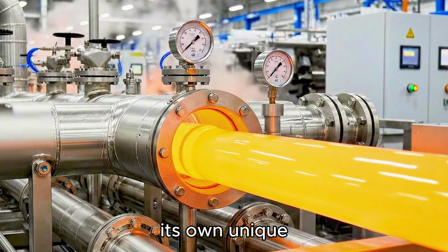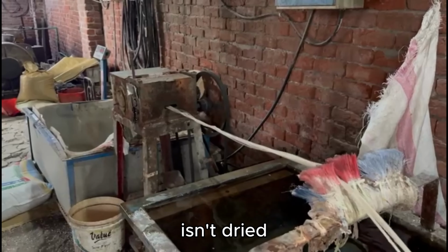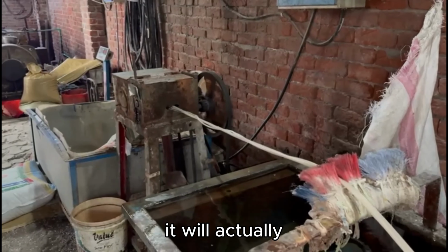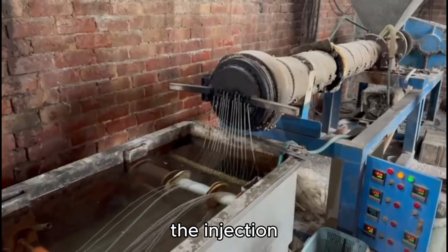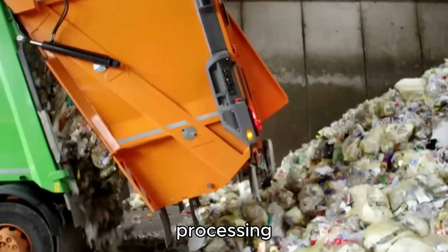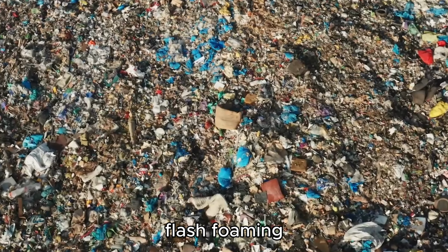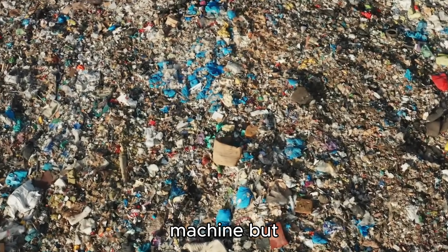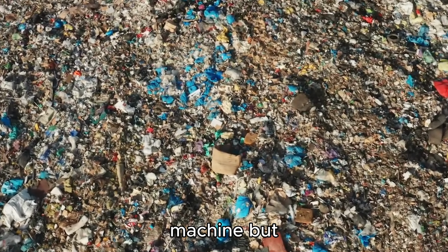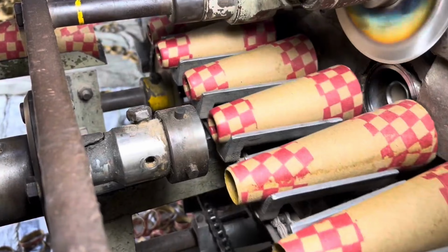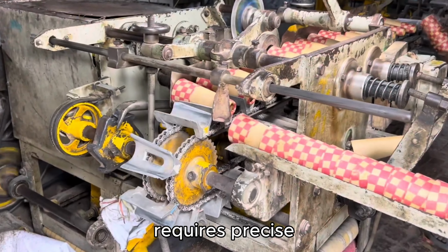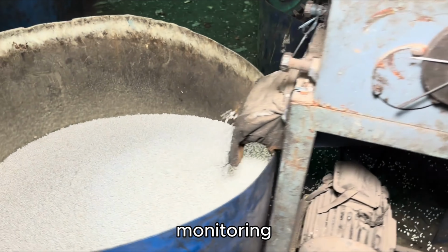Nylon presents its own unique challenges. If nylon isn't dried properly, it will actually drool or spit out of the injection molding nozzle during processing. This creates flash, foaming, and pressure drops in the molding machine. But if nylon is over-dried, the final product becomes brittle and prone to stress cracking. Finding that sweet spot requires precise control and constant monitoring.